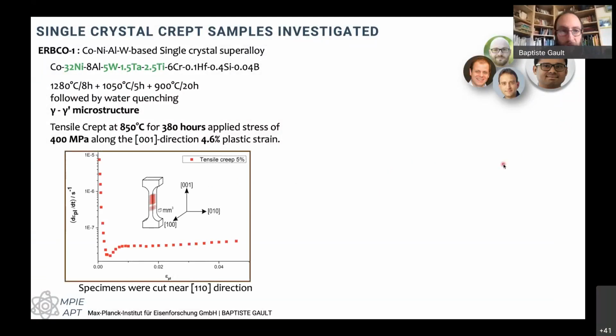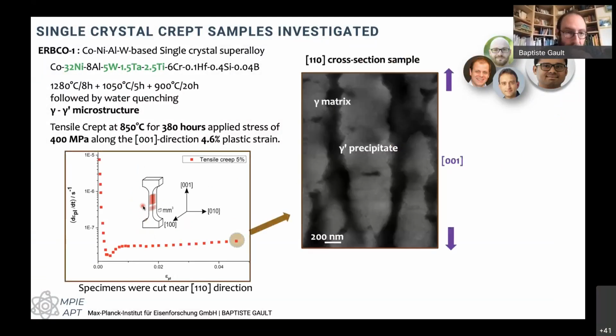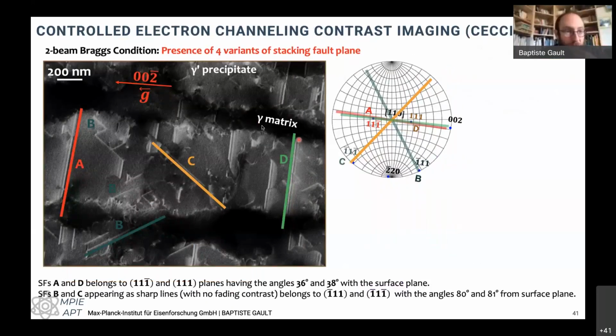But what we wanted to look at were some of these creep cobalt nickel alloys. And as they get crept to fracture, we see that these gamma prime precipitates that were initially cuboidal have extended in one direction, so-called rafting. And there are many dark features as we look through these samples in the SEM. And these correspond to stacking faults that are formed within gamma prime. So then we did electron channeling contrast imaging. I can get back to some of this if you're interested later on.